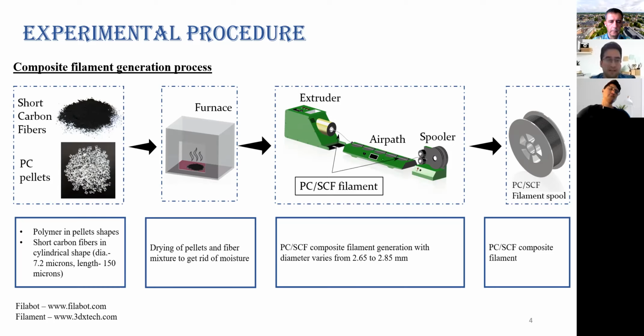So I will start. What we do is we take two different materials, one as a base material, which we call the matrix, and the second is the reinforcement material, which we take in the form of fibers. You can take powders as well. It depends upon the application. In this case, we took the fibers as a reinforcement and polycarbonate, one of the very high temperature thermoplastics, as the base material, which we call the matrix. We take those two materials, mix them thoroughly, and then dry them in a furnace.